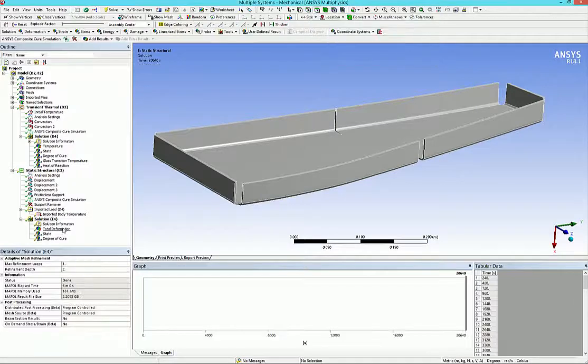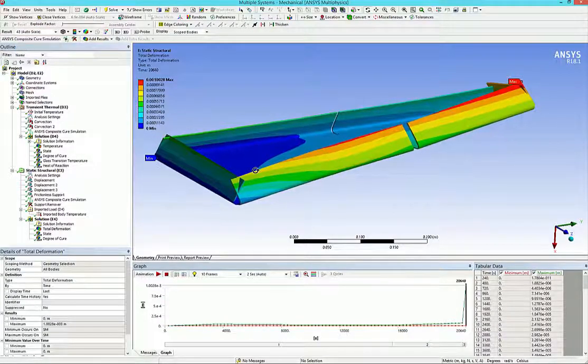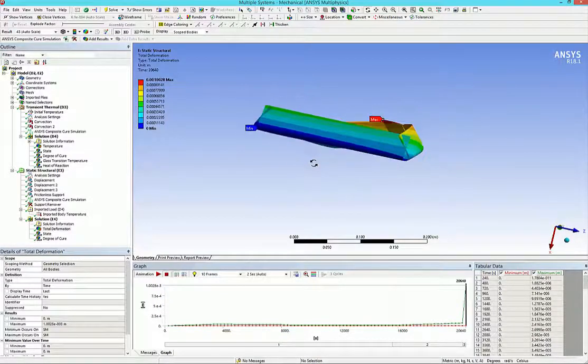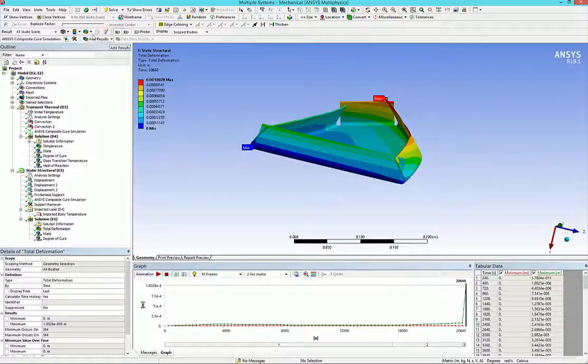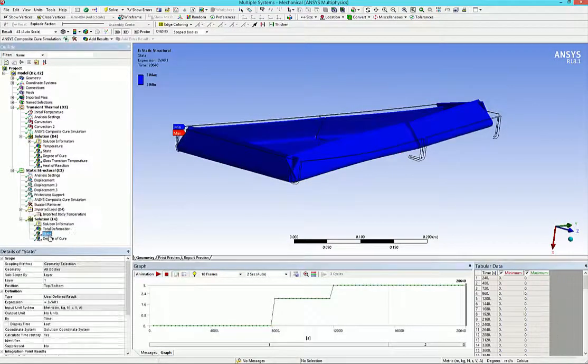The total deformation clearly shows process-induced distortions typical for L profiles. Here, the deformations are scaled by a factor of 43. Some warping is exhibited, as is the spring effect. The result can be used to compensate for the process-induced distortions from my initial design.